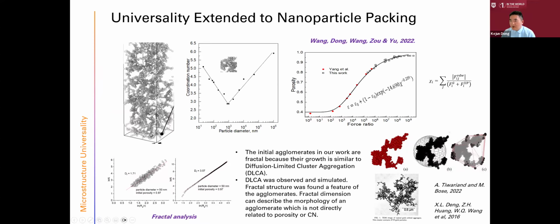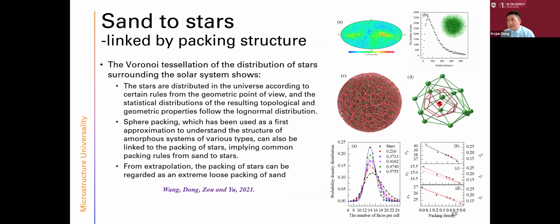But because the nanoparticles form some fractal structure, we did not successfully fully extend the microstructure universality to the nanoscale particle scale. But on the other hand, if we go to large particles, and for the universe, we can connect all the stars' coordinates, and then we think the structure can be regarded as the packing of these particles in a very loose way. So we can use what we applied in the analysis of packing of sands. We use the Voronoi to tessellate their local space, and then we analyze the local space of each star.